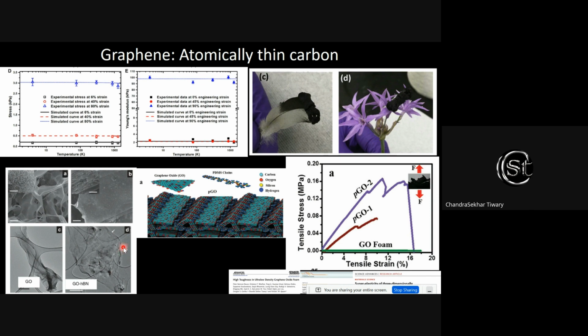So you can see if you have a graphene oxide single layer, they crumble because of their own structural weight or surface charge. Generally, they crumble. But if you put hBN in, they become flat, and you can make a much bigger single layer of material by putting hBN on graphene oxide. Now, this is just one of the works, but we end up doing a lot of this structural engineering, or I'll say atomic scale engineering, where you start putting nanoparticles or another 2D material, and you can tune its structure and hence its mechanical properties. Also, graphene or graphene oxide has a lot of surface area.